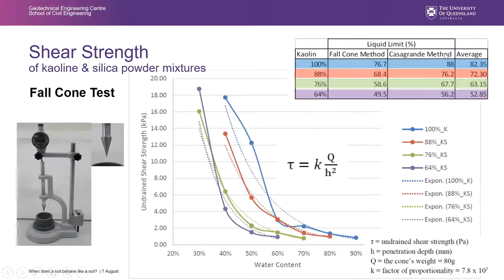Here are the liquid limits from the Casagrande method, which I've shown before. This is the substitute method, which, as you can see, gives different results. And there is the average. And this test was conducted with a so-called fall cone test. This is the substitute test for the liquid limit. So basically we fill a chamber, a cylinder, with a soil remolded at a given water content. We allow this cone to penetrate into the soil for 5 seconds. And then we look how deep that cone has penetrated into the ground. And then we can calculate the shear strength out of that penetration depth.